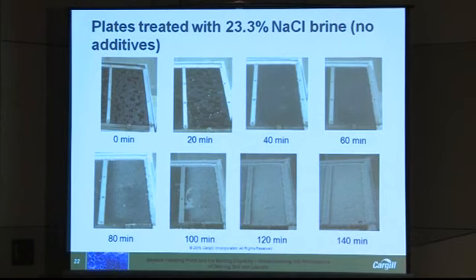As we continue to expose these coupons or these plates to freezing precipitation, for a while that transparent glaze ice continues to grow. And then after about 80 minutes, we note a transition. Suddenly we start seeing what? That same white rime ice that we saw when there was no de-icer present on the plate. And at that point, that white rime ice just takes over and it starts to build and accumulate.